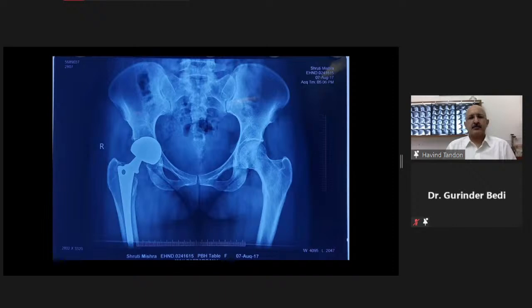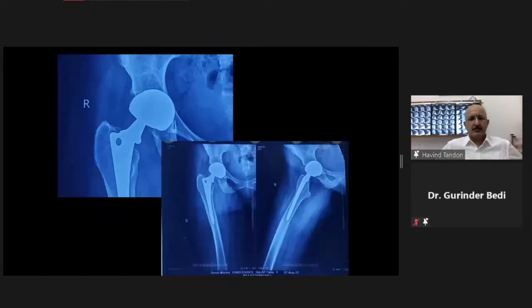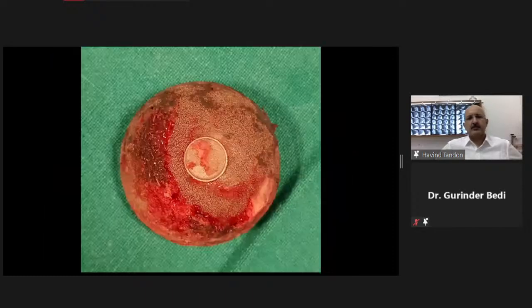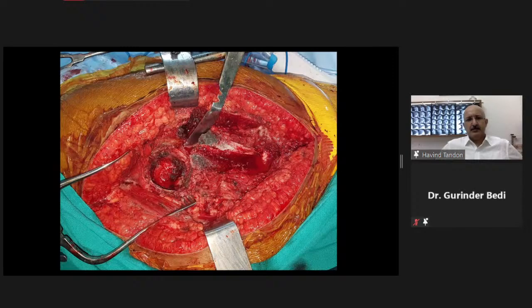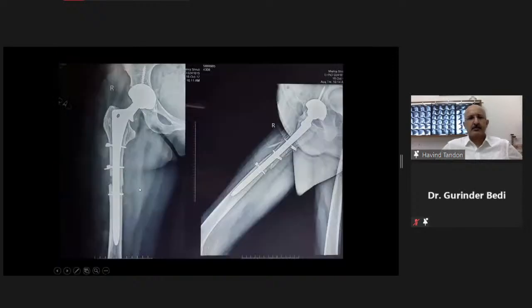Just sharing an example, a young lady with metal-on-metal pain. The cup was quite vertical. This was revised, the cup removed, and we used a highly porous cup, the tantalum shell, along with a fully porous coated stem, and she did well in follow-up.